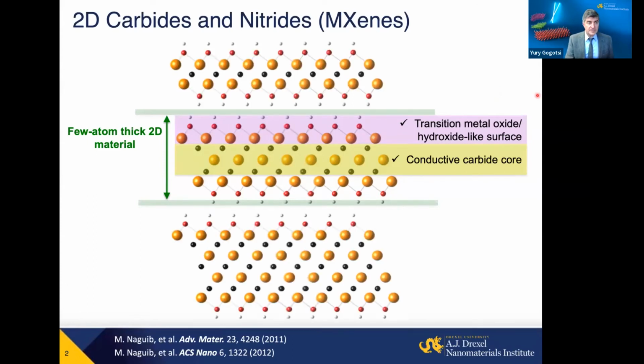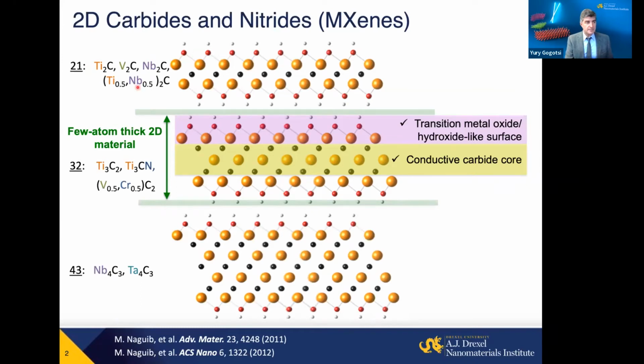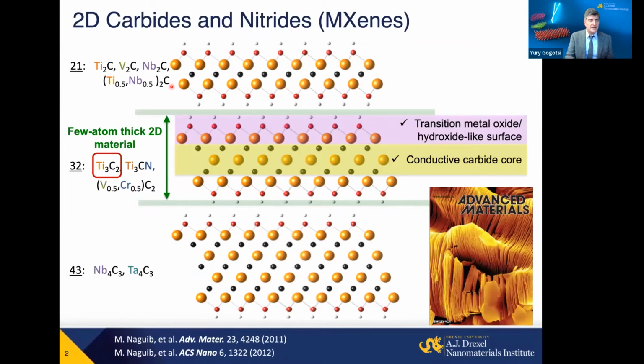But they come in many different structures. We distinguish them by the number of layers, like 2 layers of carbides and nitrides, and for example, 1 layer of carbon or nitrogen. You can have simple structures. You can make solid solutions on the M side and solid solutions on the X side. And the first one was titanium carbide, Ti3C2. It is still the most studied material, and it was published in 2011. Michael Naguib was a PhD student working with Professor Michel Barsoum and myself, and he made the first MXene.